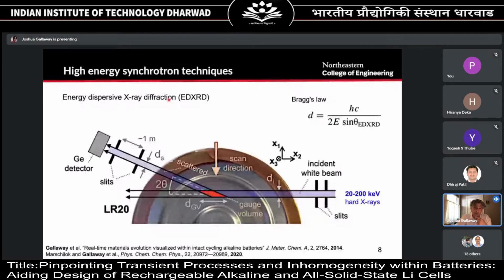In the separator between the anode and the cathode, we see nothing because there are no crystalline materials there. And then in the cathode, we see these 3 peaks, which are the cathode material. And then the outer cylinder of the battery is actually 2 layers of metal, and we see those 2 materials right here. Okay. So the reactions that happen in this battery look like this.